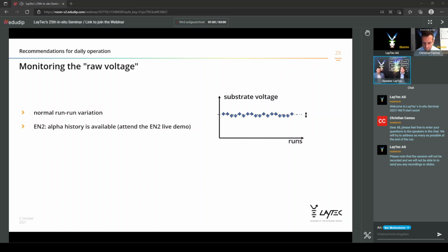So what we would expect, if the system alignment is fixed, it's correct, and the viewport is clean, is that from run to run you have a small fluctuation, but overall a straight line. You always have the same voltage since the optical path is the same. What we recommend is to insert a silicon wafer to check it, to open the window. In the afternoon session, during the live demo of the EpiNet 2, Thomas Mann will show how to do that in the EpiNet 2 and to track it.